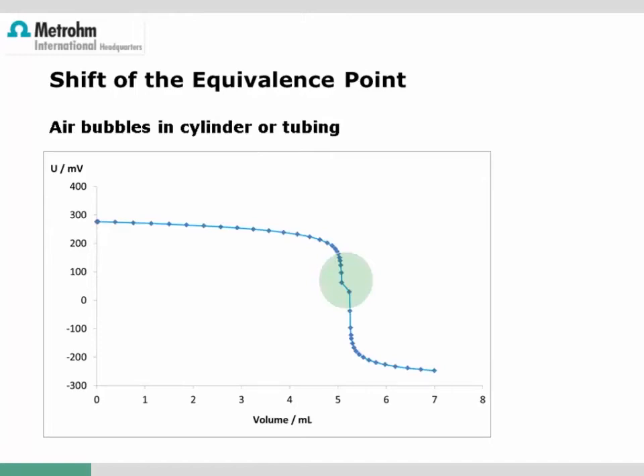Another typical application problem are air bubbles in the burette or in the tubing. All titrations are good, except one outlier with one strange bend in the titration curve that causes a shift and a wrong result. This is a typical indication for an air bubble in the titration tubing. Air instead of titrant is dosed for one or more volume increments, so there's a shift of the measuring signal on the volume axis.